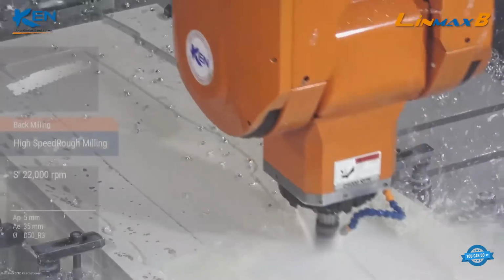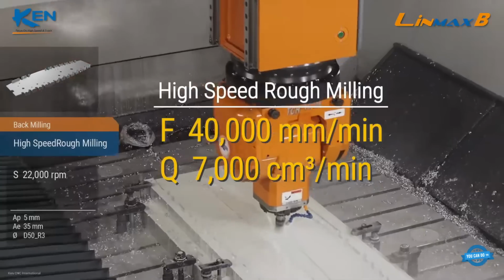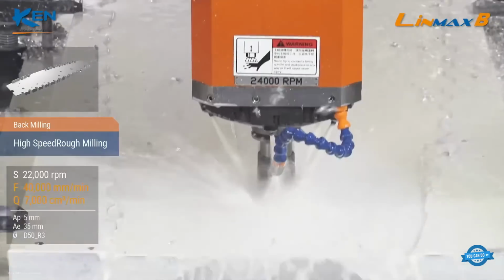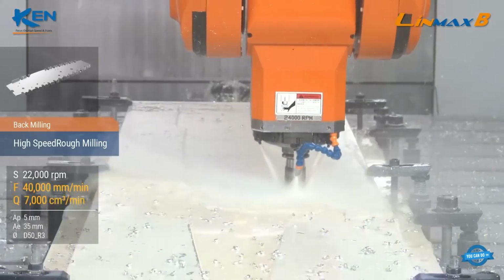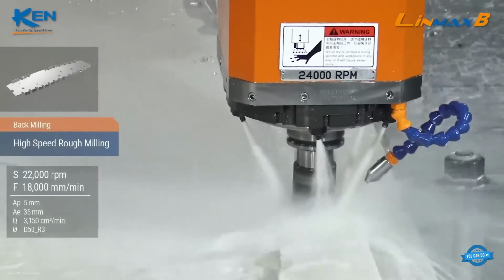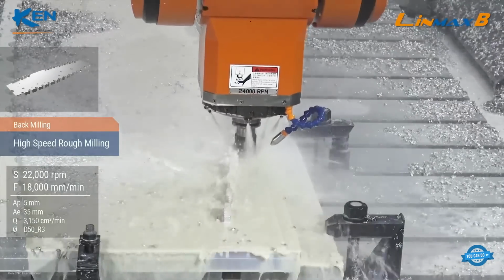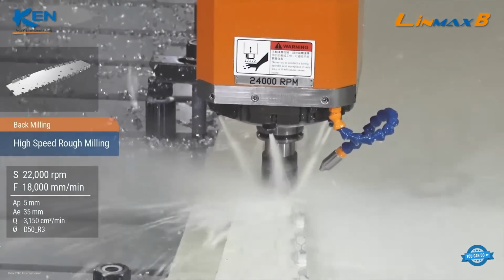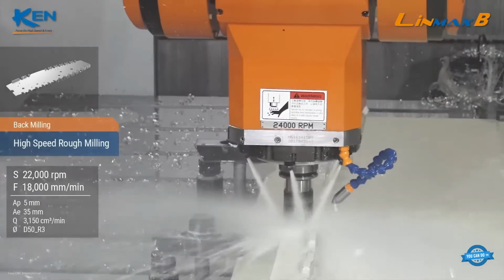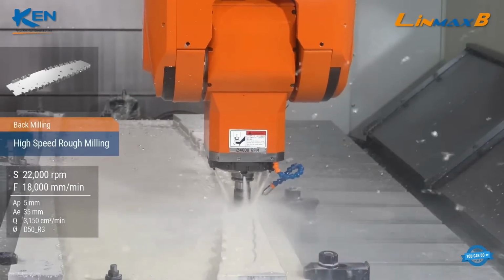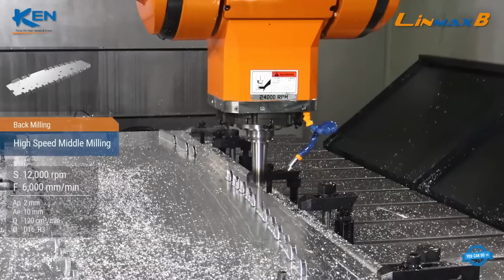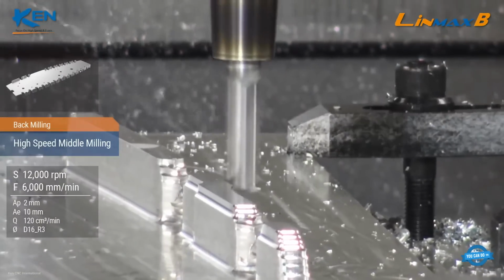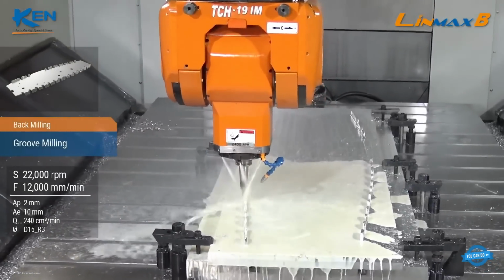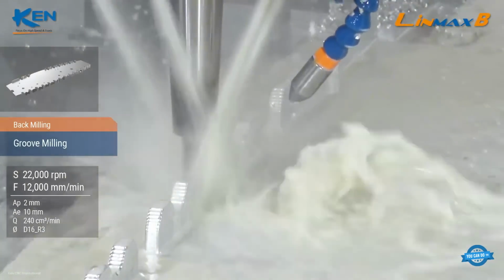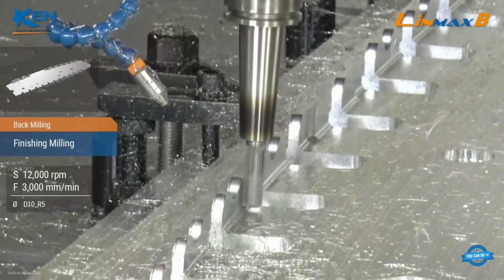Lightweight, strong, and aerodynamically critical, aircraft wing ribs demand absolute precision in every cut. These aluminum components form the internal skeleton of wings, requiring advanced machining for strength and performance. This particular wing rib, made from 6061 aluminum, measures 1,960 millimeters in length, 635 millimeters in width, and 70 millimeters in height. The process begins with high-speed front and back rough milling at 22,000 revolutions per minute, with a feed rate of 40,000 millimeters per minute and material removal rate up to 7,000 cc per minute using a D50_R3 cutter.